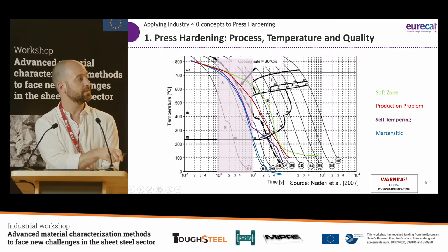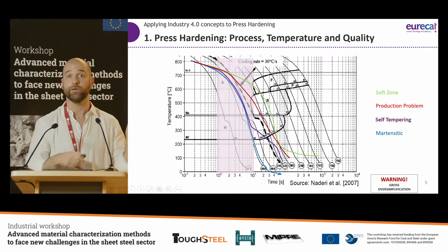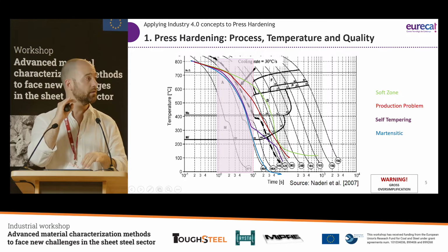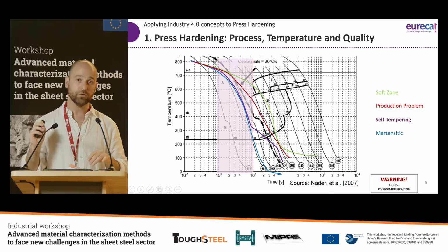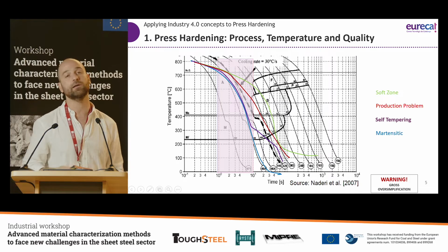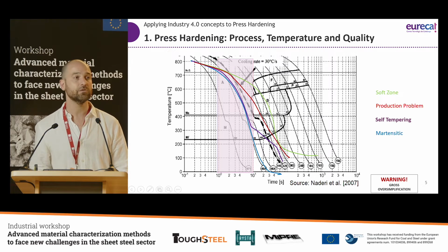So basically, just imagine that we are cooling our piece, we are following a good path, but we open the die and we take the component out before we have reached temperatures that are close to 100 degrees. And this is definitely something that can happen. And this will lead to something called self-tempering.